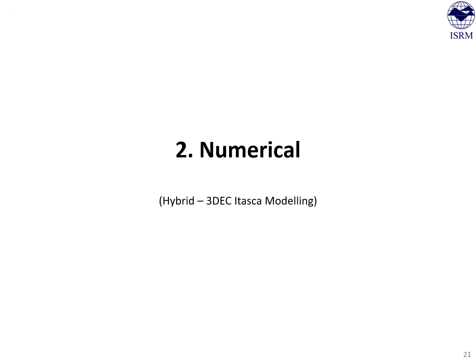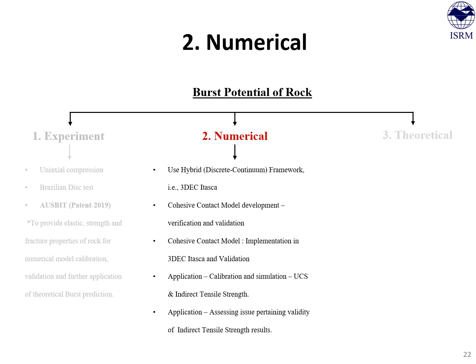After experimental, the second approach we adopted in this research is the numerical modeling approach. For this approach, we used the hybrid numerical modeling framework provided by Itasca 3DEC. The intent of this approach is to develop a 3D numerical modeling space where we can perform numerical strain burst experiments outside the calibrated dataset. For that purpose, we developed a new cohesive contact model, and we implemented that model in 3DEC Itasca. The intent here was to capture realistic or reliable cracking behavior or specimen fracture behavior under the given loading conditions.